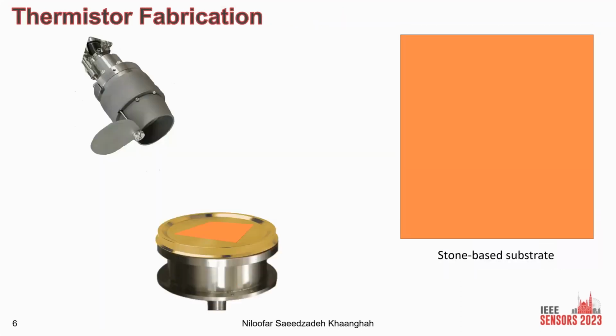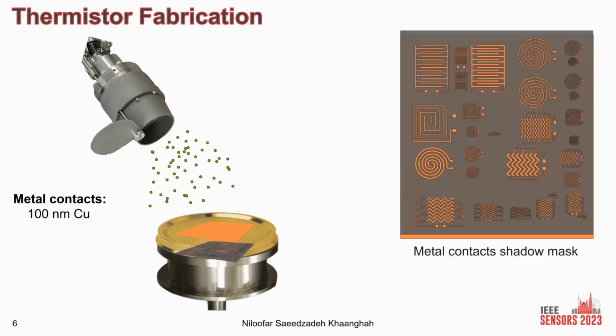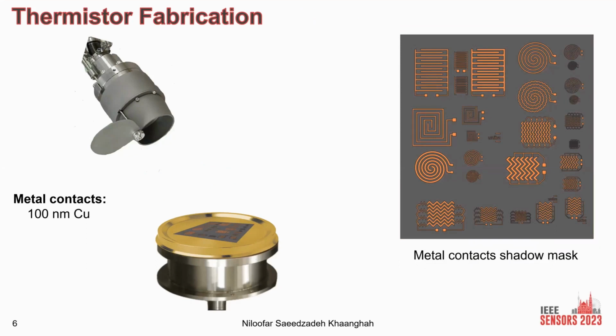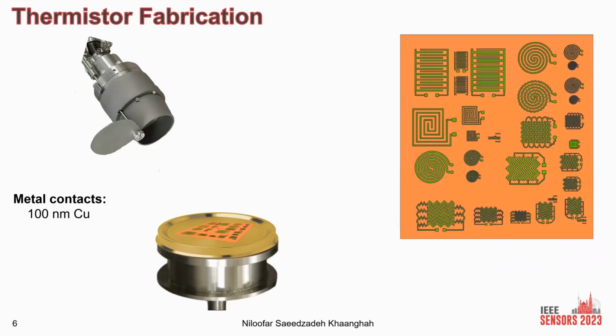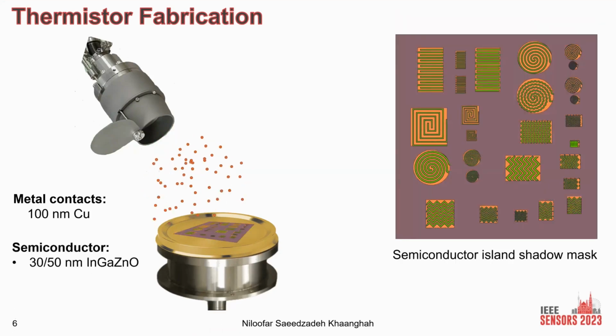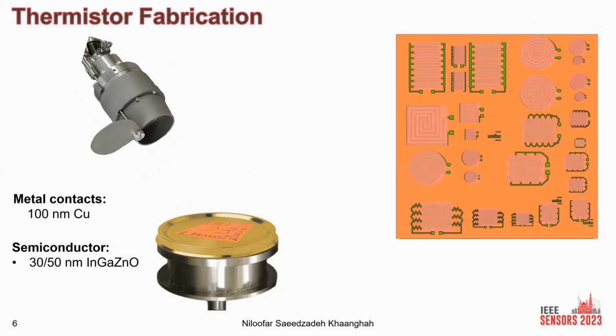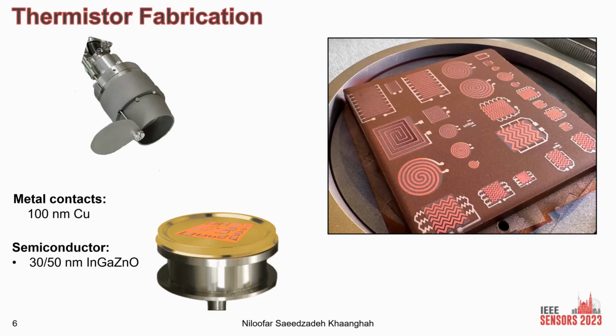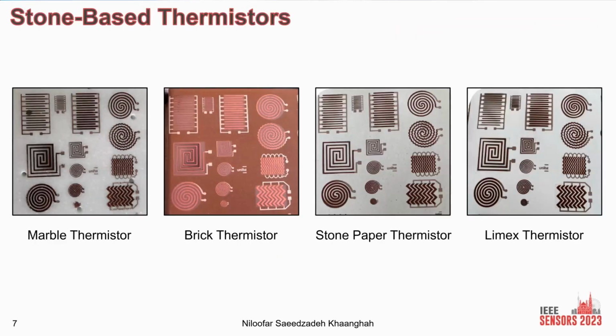So we took the substrates one by one into the sputtering tool main chamber. We used a shadow mask to sputter copper, to make metal contacts on top of the substrate. And to connect these metal contacts, we use another shadow mask and sputtered an InGaZnO semiconductor to fabricate the total thermistor, and this is how the thermistor looks after the fabrication. And this is a real 3D image of the thermistors fabricated on the brick. And here you see all the thermistors on the 4 different substrates ready to be analyzed.